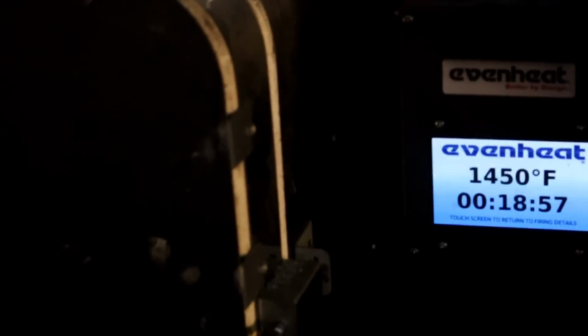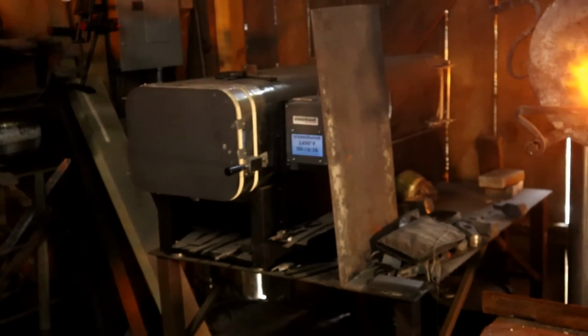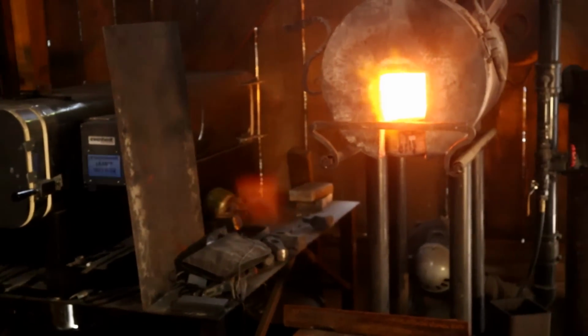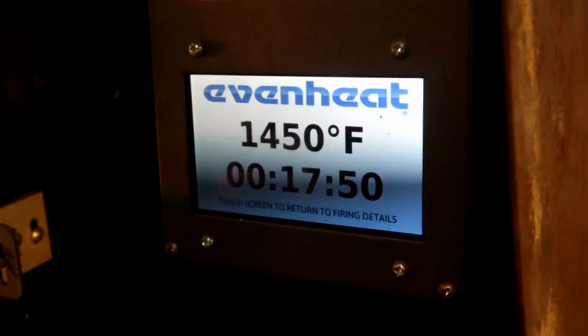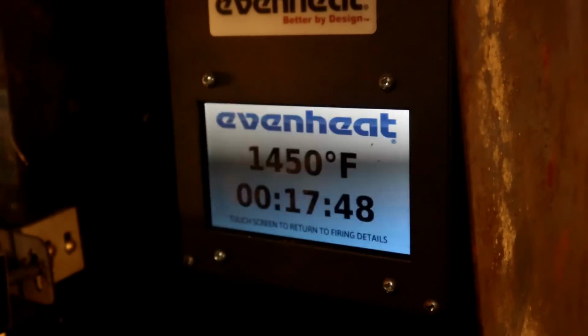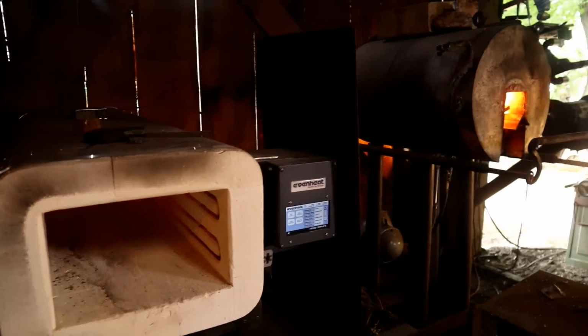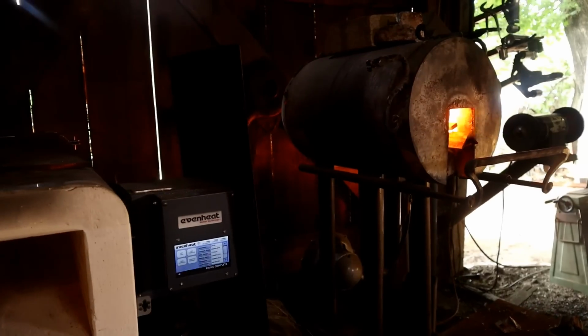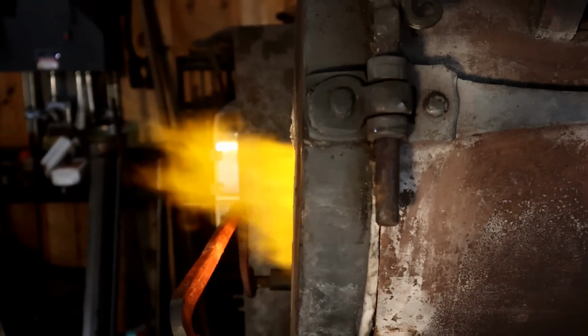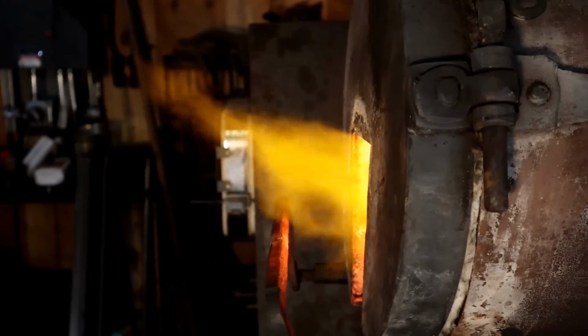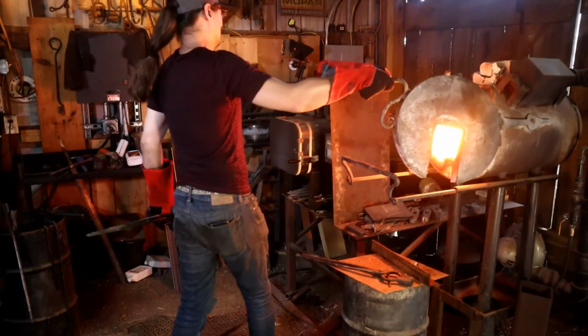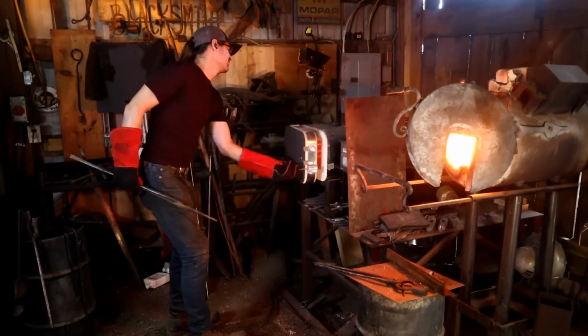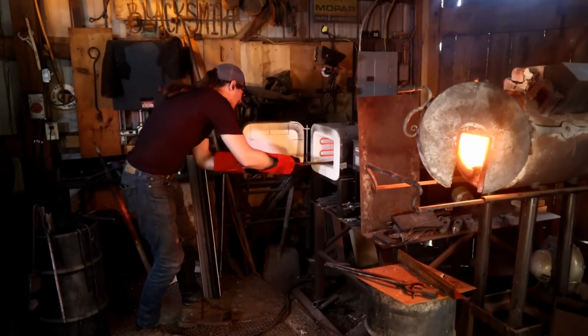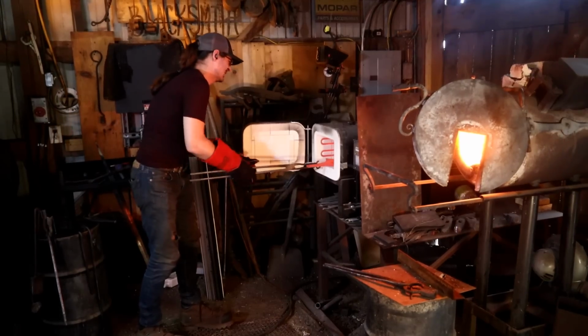To treat our H13 blade, we're going to be placing it in the Even Heat Kiln and let it slowly heat up to 1450 degrees. Once it's achieved that temperature and held there for 20 minutes, we will remove the spear, go directly to the propane forge, and rapidly heat it up to 1650 degrees. We then can remove it from the forge, clamp it in a device to keep it nice and straight, and let it slowly air cool to its full hardness.